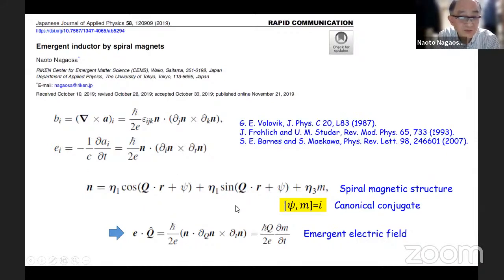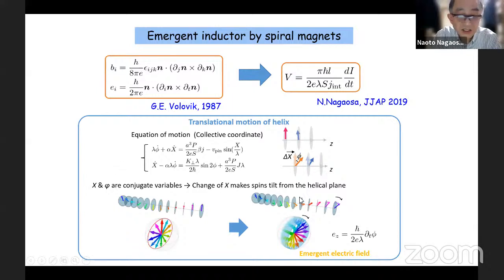So actually, if I plug this formula into this small e, then this small e has a component which is parallel to the wave number, which is given by this formula. So this capital Q is a wave number, and the M is a uniform component. So this actually leads to the inductance of this spiral. Namely, if you have AC current applied to this helical magnet, then it will shake up this magnetic structure. Especially it shakes up this uniform magnetization, the out-of-plane magnetic component. The angle is given by phi, and the x is the translational motion of this helix. And this x and phi are canonically conjugate with each other and obey the equation of motion.